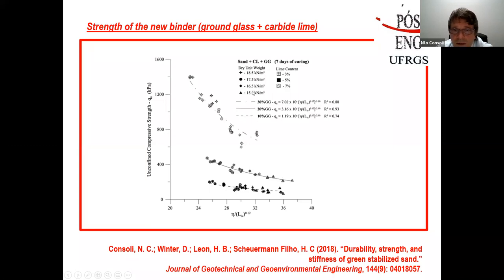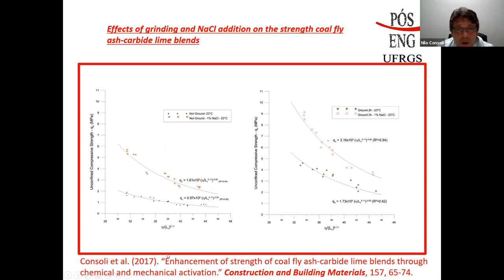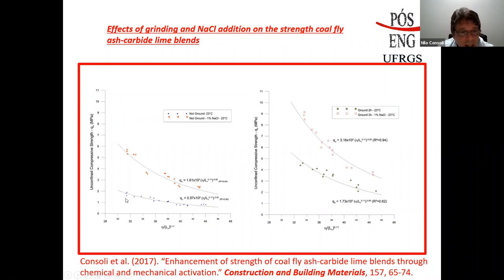Here are results for green-stabilized sand — carbide lime or hydrated lime with ground glass — also showing unique curves. Additionally, with coal fly ash and carbide lime, varying amounts of lime, ground glass, and dry unit weight, we again obtain a unique curve for the porosity-binder index.